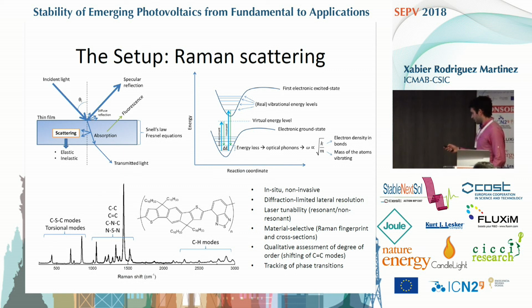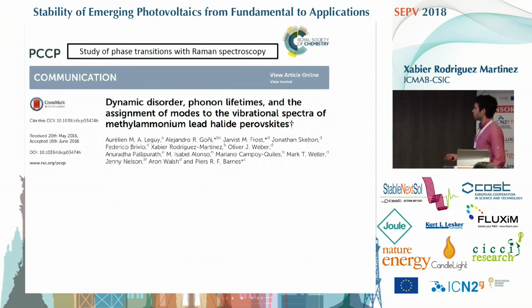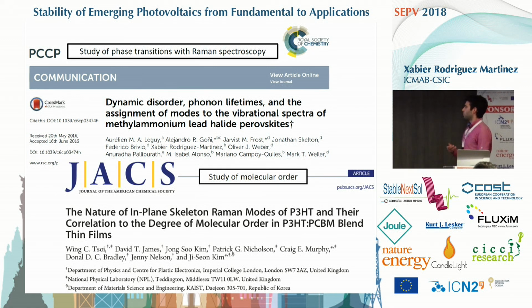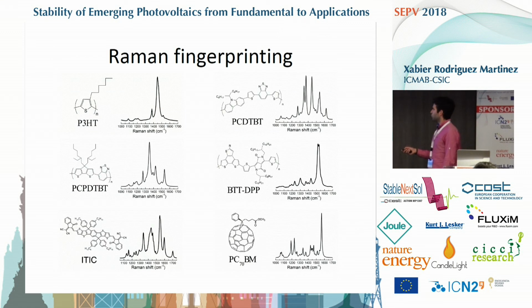One of the most interesting uses of Raman spectroscopy is, for example, the work we carried out on methylammonium lead halide perovskites, in collaboration with Imperial College, in which we studied the phase transitions with Raman spectroscopy in these materials. And apart from phase transitions, we can also study, for example, the degree of molecular order in polymer-fullerene blends, also with Raman spectroscopy. Because I don't have too much time, I cannot enter into the details of these two papers, but I will focus, for example, on the fingerprinting capabilities of Raman spectroscopy in polymers.